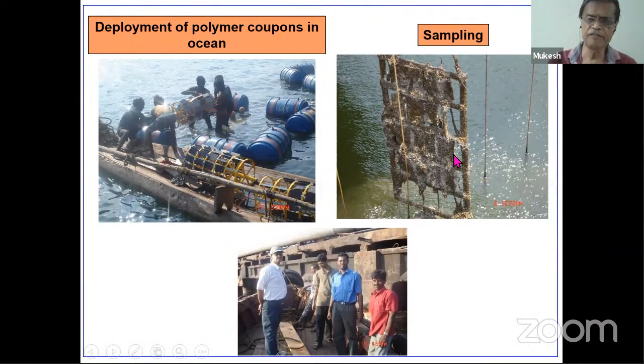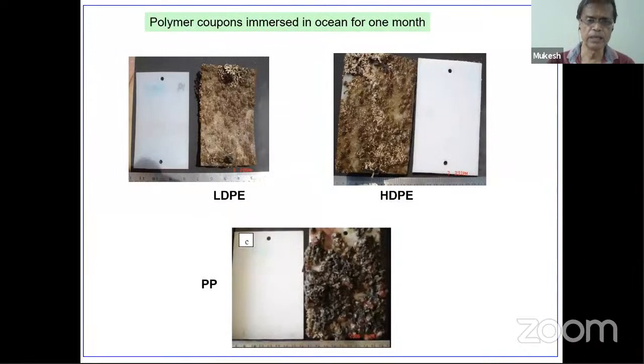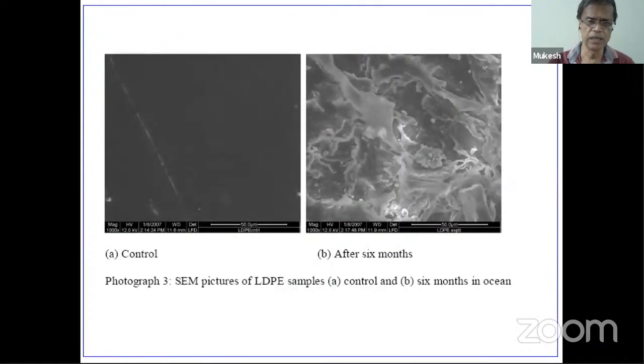Okay. And then we find out whether the material has lost weight, how much biofouling on each of these materials has taken place. Different types of materials we studied which are used in the marine industry. Okay, as you can see, low density polyethylene. In 1 month, you can see the amount of biofouling, high density polyethylene, polypropylene. Look at the large biofouling that has taken place on these materials. Look at the scanning electron picture. The surface of this polymer has really deteriorated after 6 months. Okay, so it's not only biodegradation but also biodeterioration because of the ocean currents as well.